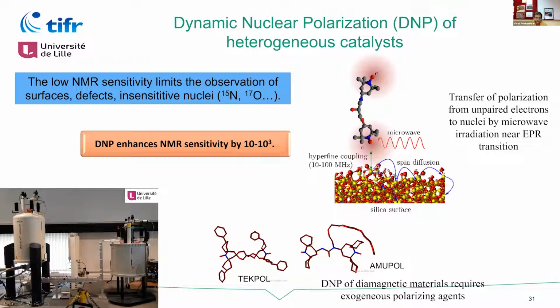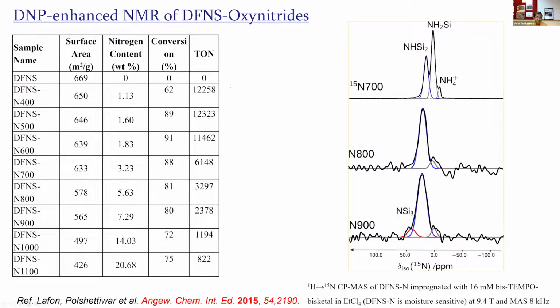And using these techniques, first we answered the question of what happens if I treat the silica with ammonia, where you replace the silanol with different kinds of amine, primary, secondary, tertiary, and we explained that it has to be primary and secondary amine if you want to get good specificity rather than tertiary amine. This was very debatable, but then we used solid NMR and DNP enhanced NMR to really prove that it is the primary and secondary amines which are the cause of the basicity rather than the tertiary amine. These amines are connected with silicon.